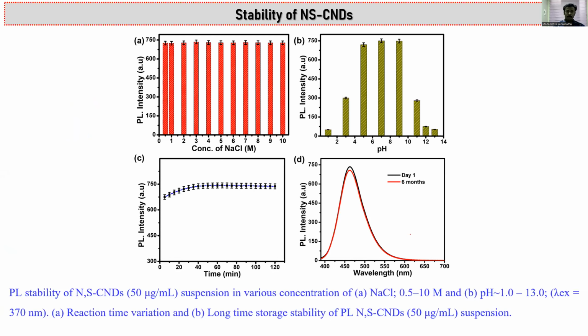The next one is the stability studies. We know very well that we have to optimize the carbon dots and verify the stability of the nitrogen and sulfur carbon dots against pH levels, sodium chloride salt ionic concentration, different reaction times, and the storage stability. These carbon dots are maximally stable up to a salt ionic strength of 0 to 10 molar, and highly stable, and in pH the maximum is at neutral pH.